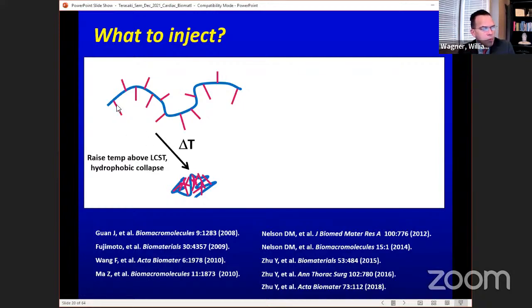So here's how we did it. We used the N-isopropyl acrylamide chemistry, which is well known in the field. And that has a isopropyl group that gives you this inverted thermal responsiveness. So basically, as you raise the temperature, it collapses. It sheds its water and collapses hydrophobically. So we have a backbone here that has isopropyl groups on it, and isopropyl acrylamide, and some other groups. But then we have these side branches that are hydrophobic, and they have at least one labile group associated with them. So you raise the temperature, these will collapse. So that's design parameter number one. It goes from low viscosity to being elastomer or viscoelastic.